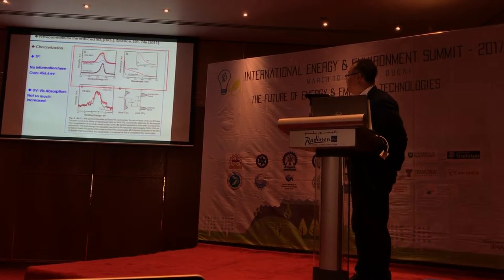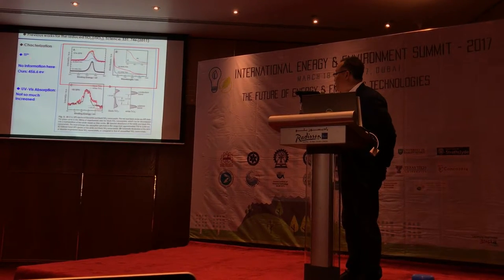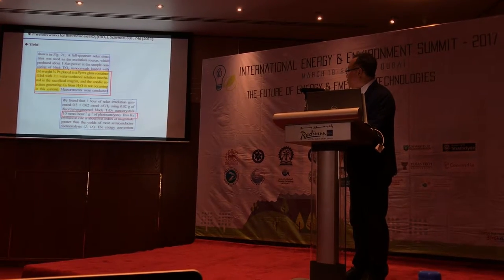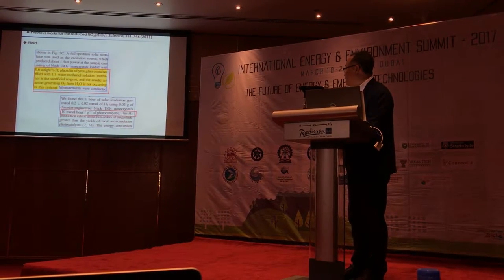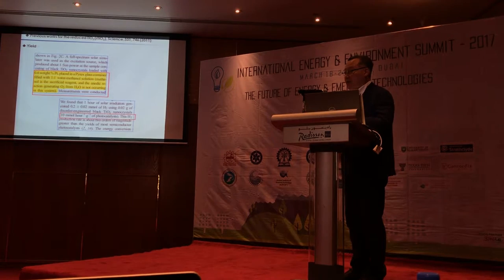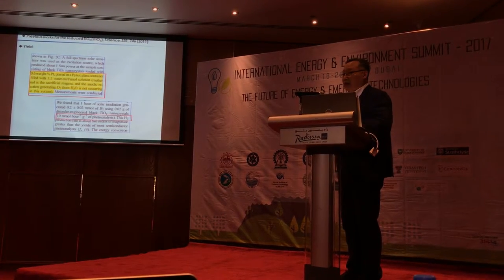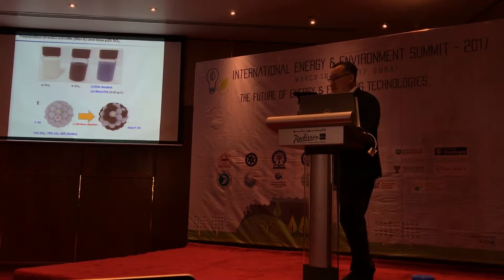The science paper shows they made the black one based on hydrogen conditions, reducing from Ti⁴⁺ to Ti³⁺. This is the evidence from XPS. They checked with 0.1 wt% platinum, giving about 10 millimoles per hour of hydrogen gas. This is the world's best at that time for making black titanium dioxide.